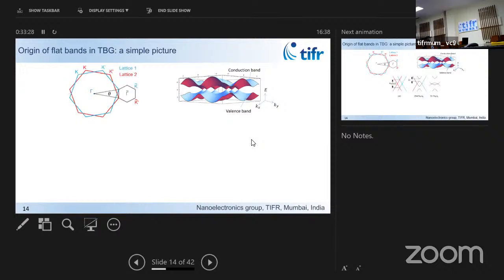Once you have that, if you twist it, you get another Brillouin zone, which is rotated by the same angle as the rotation of the original lattice in real space. That superlattice periodicity gives rise to another Brillouin zone, called the moiré Brillouin zone, which is this. What happens here is that if you look at these points, you have a Dirac cone at each of these, red and blue. They come close to each other because of the rotation, and when they come close to each other, they will actually hybridize when they overlap.